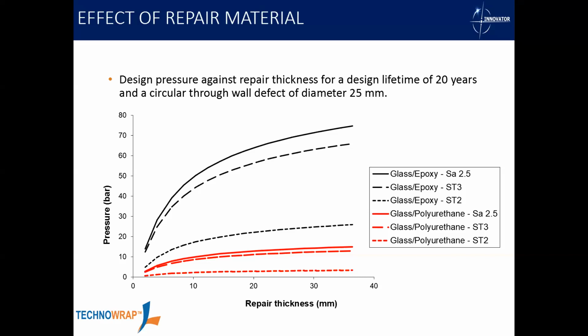I would see the polyurethane as a quick fix, a very, very short-term solution. In terms of short-term, I would say days up to a week or so. Whereas the engineered repairs, we're saying 20 years, possibly longer, depending on the scenario. And there are some manufacturers out there who push this product like it is the solution to everything. Quite frankly, the way these water activated products are being pushed in the industry is like those commercials on television with Flex Spray and Flex Wrap, the stuff you can buy at Canadian Tire. It's no different, and it gets you similar results.